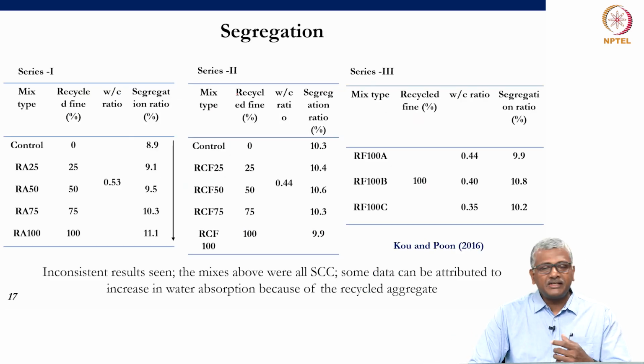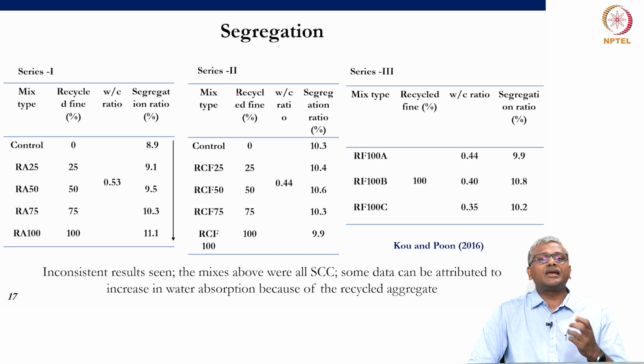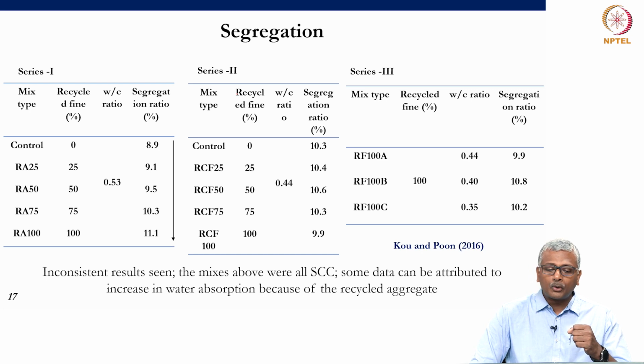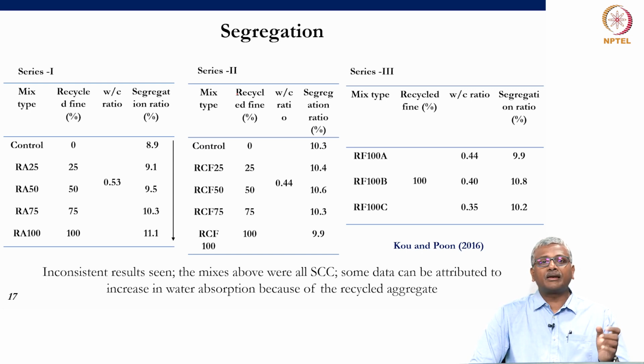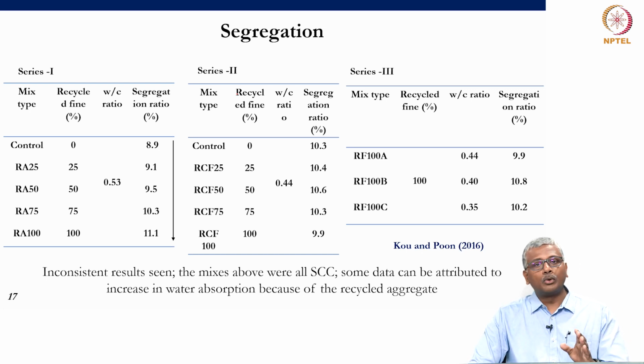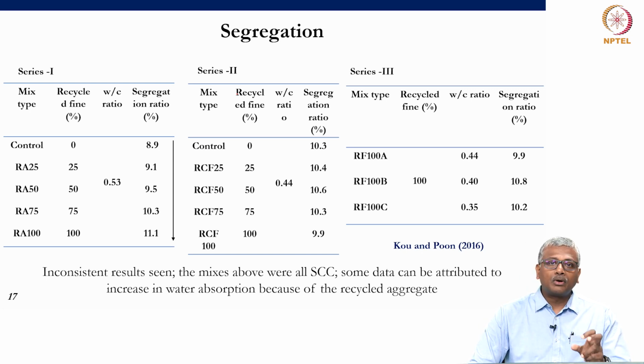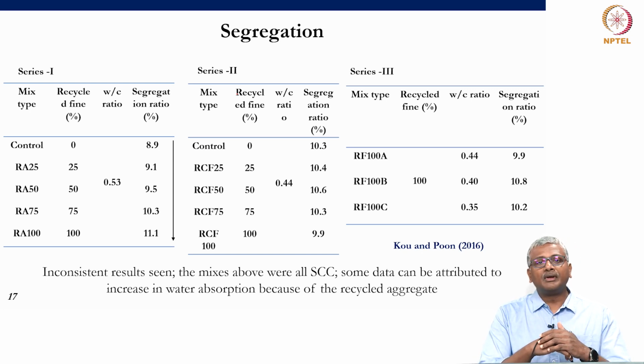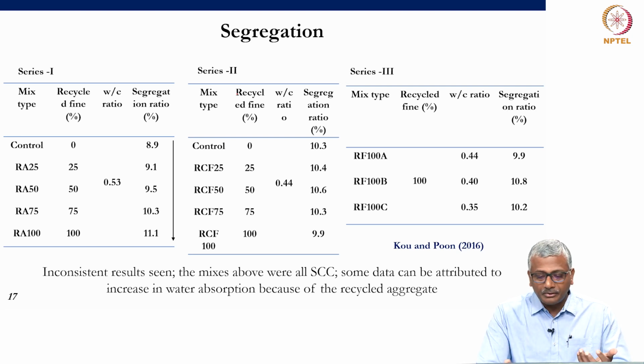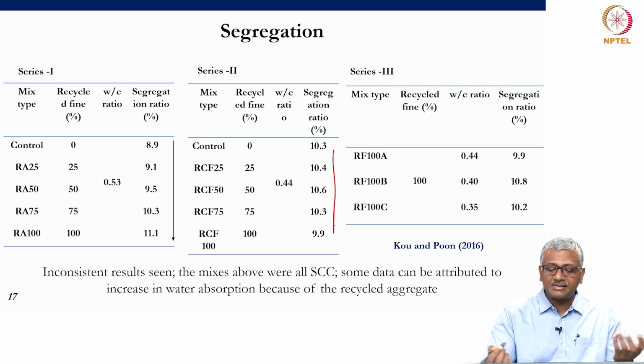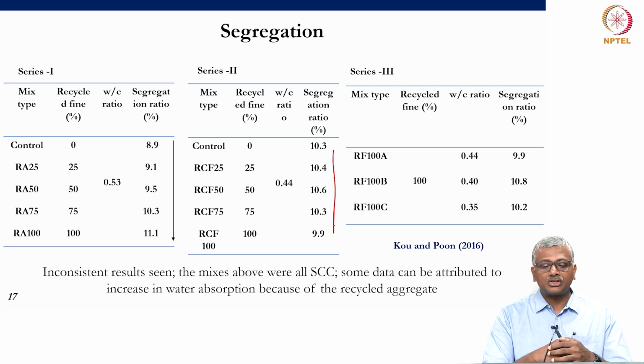Now, there have been studies that have defined segregation levels with different types of concrete. There was one study by Kou and Poon where they looked at replacement of conventional aggregate by recycled concrete aggregate both in the coarse and fine aggregate regimes. In such cases, what they wanted to determine was how much was the potential for segregation of the concrete mixes when they replaced normal aggregate with recycled aggregate. Now, the results which are presented on this slide are quite mixed. You can see that in some instances you do not really see a major change in the segregation ratio.